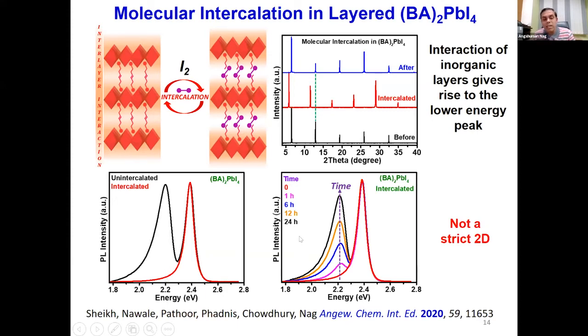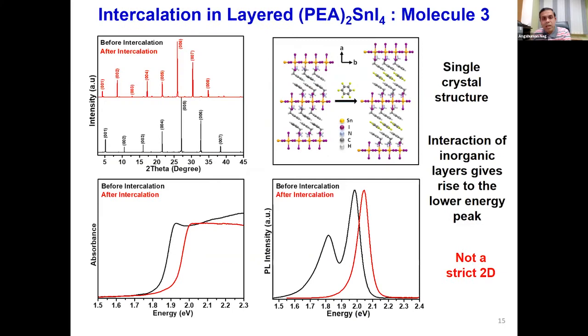Interestingly, as I told, this intercalation is a reversible process, and iodine comes out with time, and you see that with time the lower energy peak reappears, and its intensity increases enormously when the iodine gets de-intercalated. The same thing is shown here for another crystal, a phenylethylammonium tin iodide system with different molecules. I'm not discussing this slide.